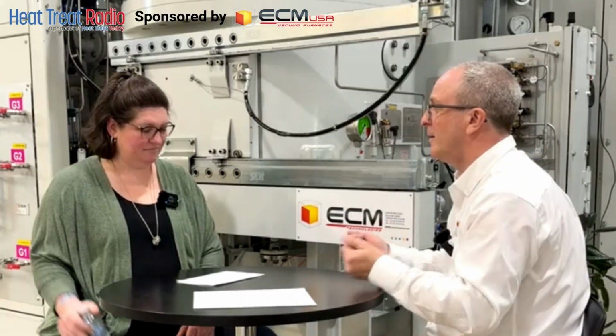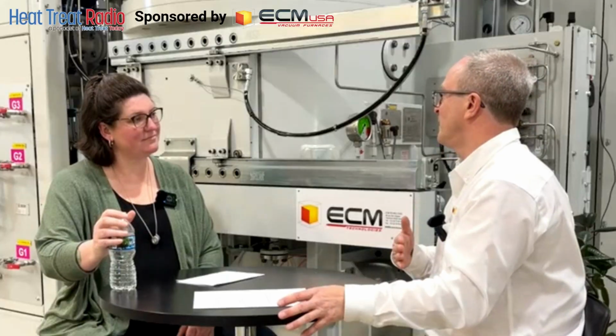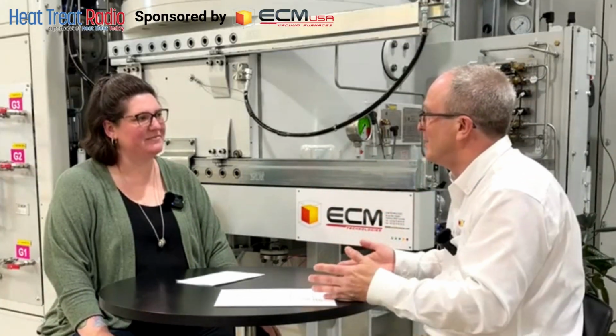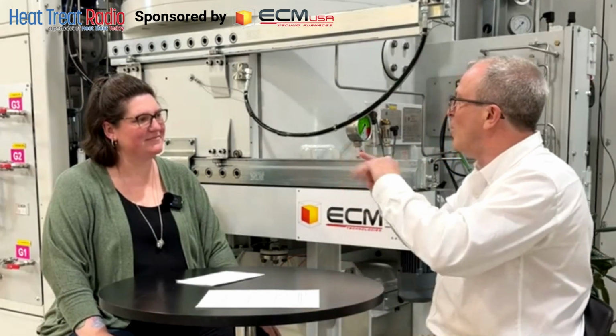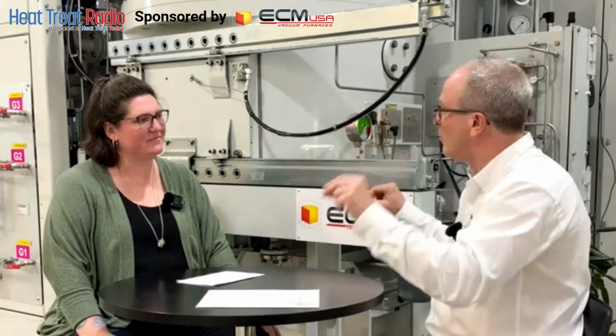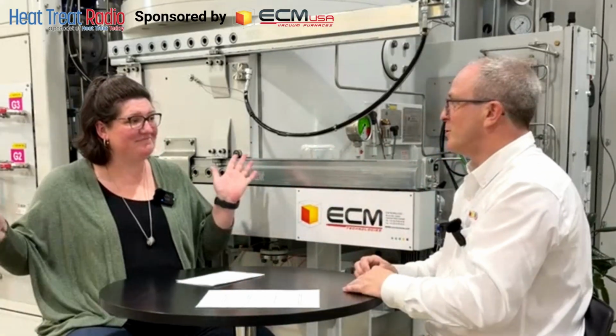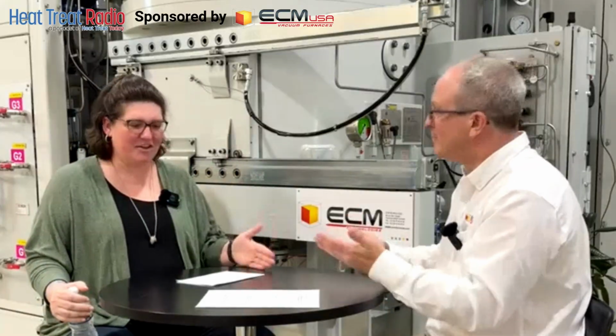But it's like an atmosphere furnace. I work with atmosphere furnaces, and every atmosphere furnace has their cheat sheet. Don't let the NADCAP auditor see, just hide that. True. But you need carbon potential, you need your temperature, time, and pretty much in vacuum carburizing it's the same thing. It's temperature, your carbon potential, or what you expect for carbon, and the time, so the case depth you would like to achieve, and here is your process. And then you don't need the cheat sheet. Pretty much, no, it's gone. Then it's documented, repeatable.